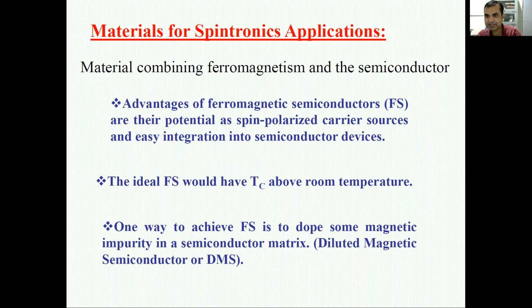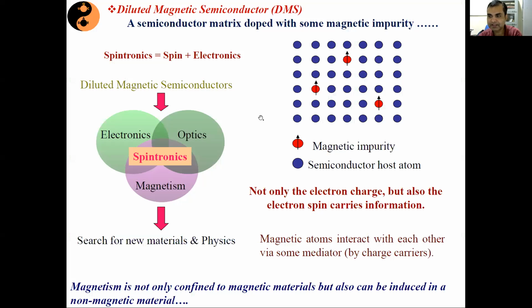In dilute magnetic semiconductors, you dope magnetic impurity in a semiconducting host matrix with the intention that these magnetic impurities which we are doping in the system do not form a cluster of their own. So the magnetic information is not coming from the magnetic clusters only, rather that magnetic information is coming from the spin polarized carriers in the system. That is a very important aspect.